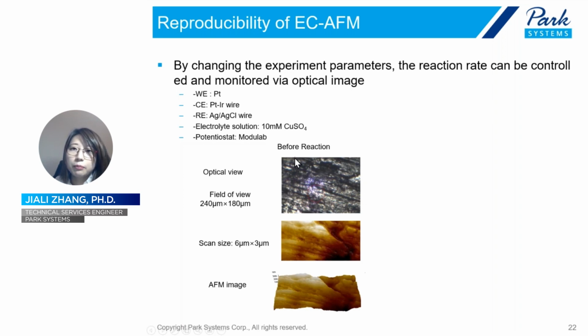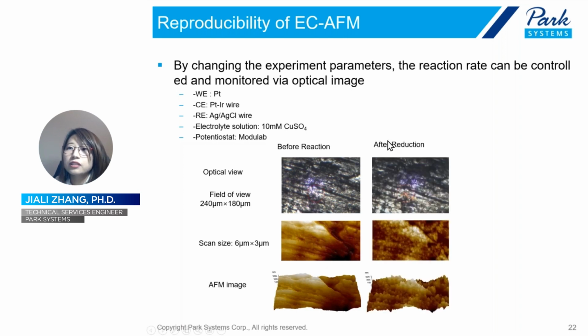Here is an example. Before the reaction, the platinum surface is black, and the platinum surface AFM image is also shown here. And then after the reduction, the brownish copper color is shown in the optical view, and also small domains of copper show up in the AFM images.